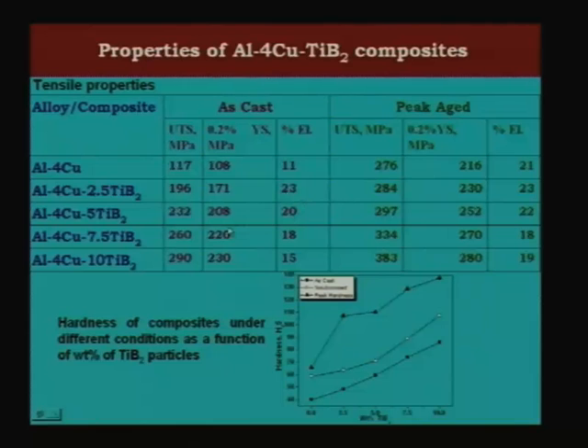In the as cast condition itself, you reach about 290, and if you age it, you get about 380 MPa, which is much higher. You can compare without any reinforcement, the highest that you can achieve even in the peak aging condition is only about 276, and almost about 100 MPa increase is possible with TiB2, and the ductility still remains almost 19%. After aging, the percentage elongation increases. This is only because of the fine TiB2. Because this does not happen if you do ex-situ.